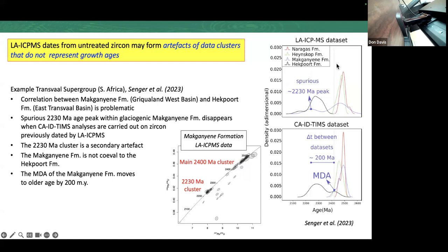So it removes not only the alteration, but the radiation damage parts. And I found that to my dismay once when I had beautiful high uranium zircons from a gabbro that I tried in my early stages of using chemical abrasion. And of course, after a couple of hours, they totally disappeared and I was left with nothing.